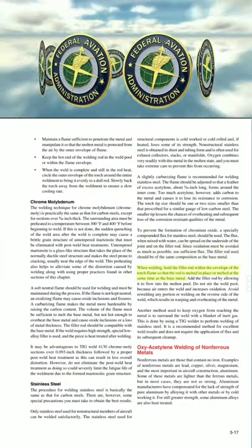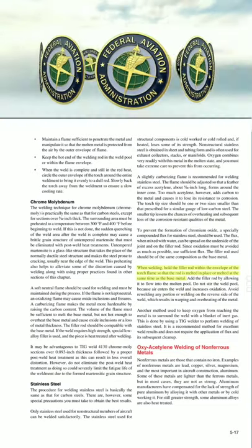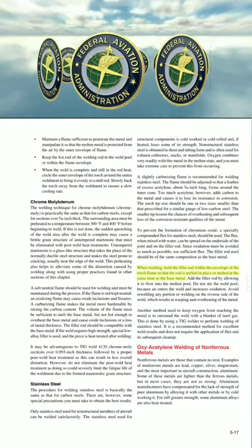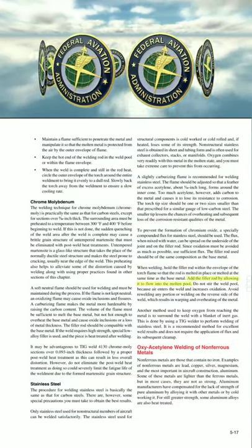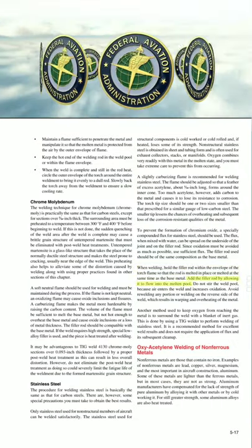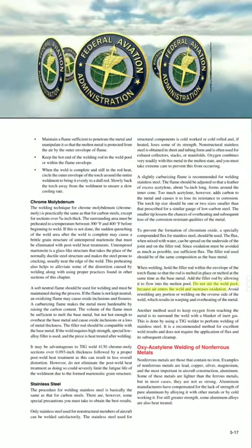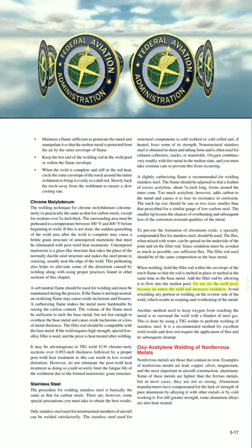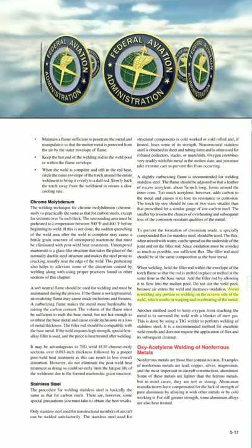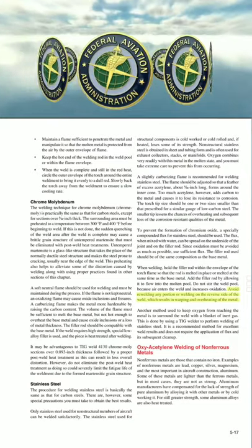When welding, hold the filler rod within the envelope of the torch flame so that the rod is melted in place or melted at the same time as the base metal. Add the filler rod by allowing it to flow into the molten pool. Do not stir the weld pool because air enters the weld and increases oxidation. Avoid rewelding any portion or welding on the reverse side of the weld, which results in warping and overheating of